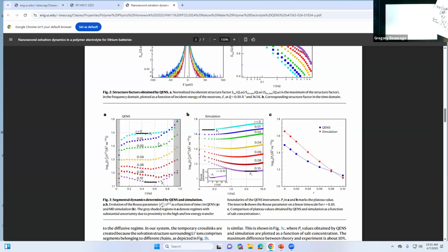You'll see this in papers. I know from scattering, log I versus log Q, you have -4, which is like a clump of something, like some goo. And then say you have sheet structure, so it's going to go -2, and then it'll go to -4 again. So for this -2, there's a thing that can be called a Kratky plot, or a Lorentzian correction. So you do IQ² versus Q. It's similar to what he did. And then you find out that at -2, that's flat.